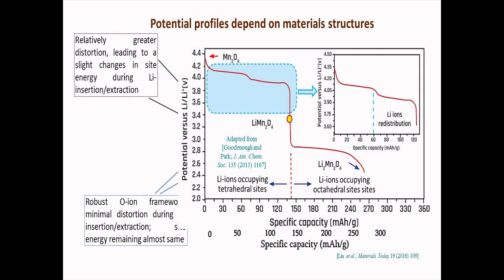However, here the lithium ion is going into the tetrahedral site, the smaller site, and here the lithium ion is going into the slightly bigger octahedral site, and that makes a difference in the energy and accordingly the voltage, which one sees as the voltage output. And that is simply because one needs to spend more energy to extract a lithium from the smaller tetrahedral site as compared to an octahedral site. So it's the energy difference which leads to a huge jump in the voltage.